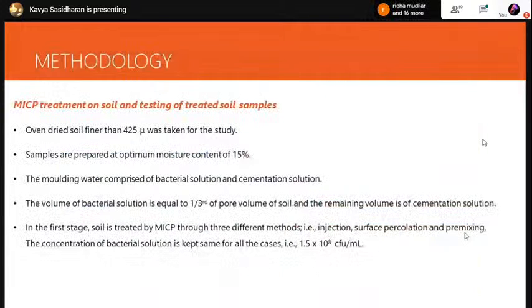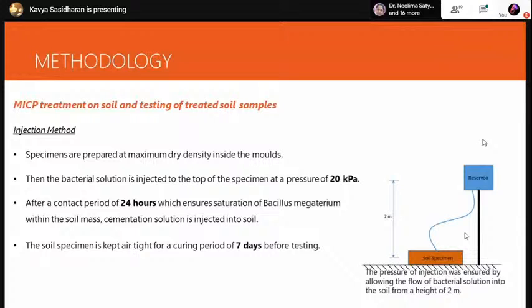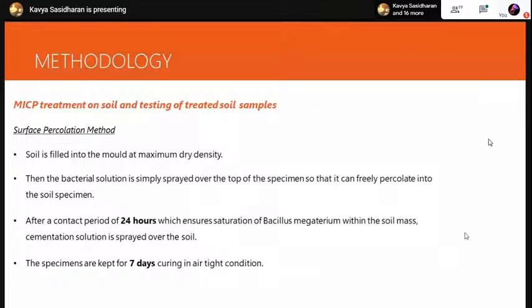For the study, oven-dried soil finer than 425 micron was taken, and the samples were prepared at optimum moisture content, and the molding water comprised of bacterial solution and cementation solution, with 1/3 of the pore volume of soil taken as bacterial solution and the remaining as cementation solution. In the first stage, the soil was treated through three different methods, in which the bacterial solution concentration was kept the same, and a curing period of 7 days was given. First is the injection method, in which the solution was injected at a pressure of 20 kilopascal, and a rest period of 24 hours was given between the injection of bacterial solution and cementation solution. Next are the surface percolation method and premixing method.